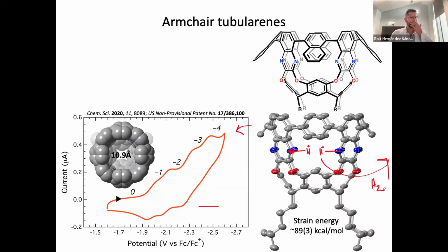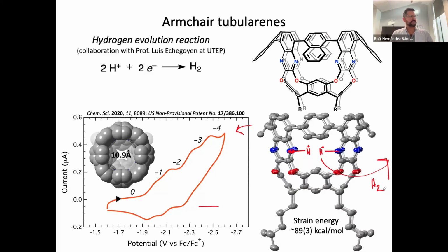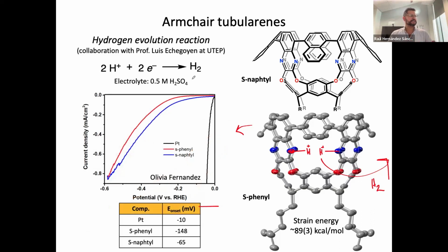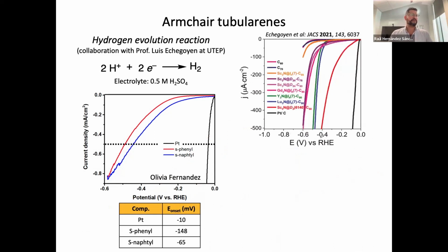And so we started thinking and collaborating with people in the field, in this case specifically with Professor Echegoyen at UTEP. And what Olivia found was that this compound has a very low onset potential for hydrogen evolution. It's actually comparable or even better than the best fullerene species that they had studied at the time. That is a scandium nitride D3 C68, which is something that is extremely difficult to obtain.